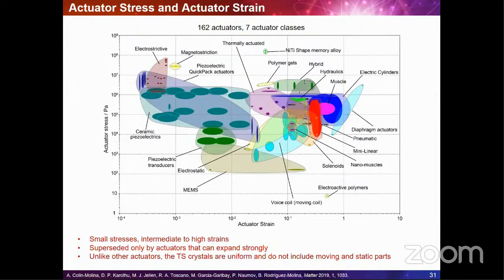This results in relatively small actuating stresses at intermediate values of the actuating strain. However, it is important to note here that the thermosalient crystals undergo large changes in size, and this is reflected in high strain of these materials. In fact, the strain exerted by these materials is comparable to those of other thermal actuators, shape memory alloys, polymer gels, solenoids, and also some hybrid actuators, which are, for example, piezoelectrics, electrostrictors, and magnetostrictors.